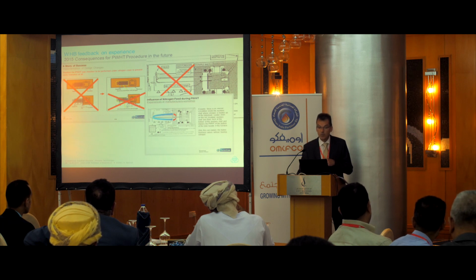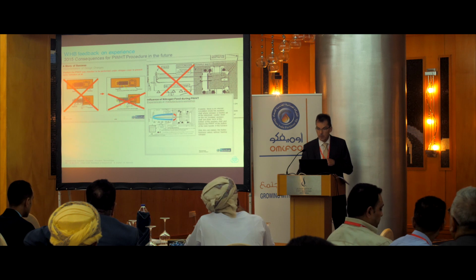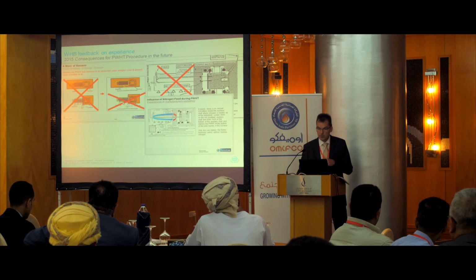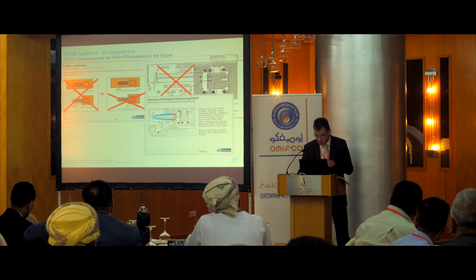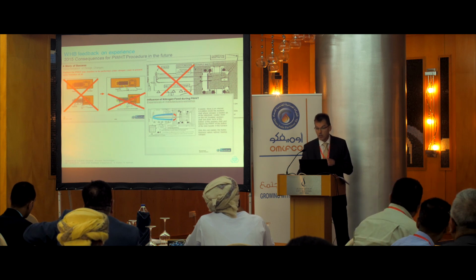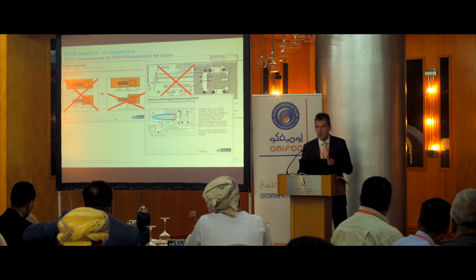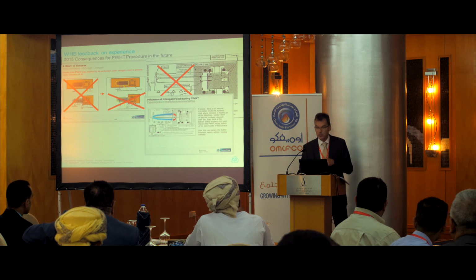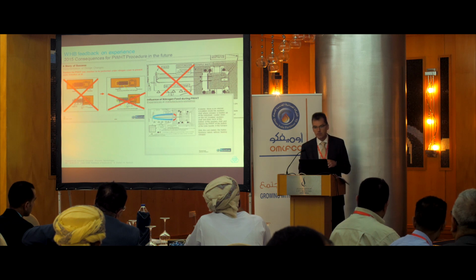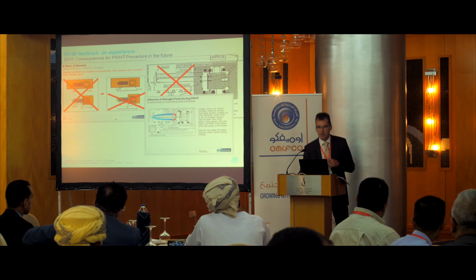Then we said, okay, if you have a furnace which has only a small size, you can do it, but you have to shield the outside bundle with an auxiliary shell, with nitrogen fed in. This is now also forbidden because we recognized that when we have cracks and feed in nitrogen, we have the circulation shown here on the bottom side. So nowadays we only allow complete heat treatment of the equipment in one furnace, with auxiliary shell and with nitrogen feeding, of course, into the shell. And if the shell gets cracks, it doesn't matter. The pressure of the nitrogen outside and inside the furnace is nearly the same. Nitrogen will not disappear immediately out of this casing.